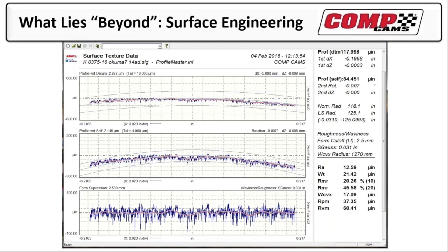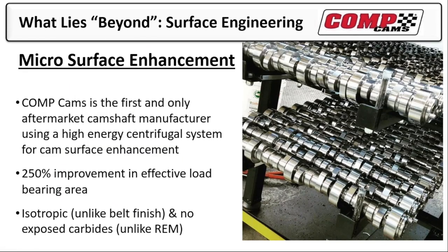About 2016, 2017, we started to go to a crown dress on all our rollers. And you can see this is very similar, but we're slightly convex. When you start looking at this, this is 300 micro inches plus and minus. Fine talcum powder is bigger than this whole scale. But you can see how we drop about 100 millionths, about a tenth of a thousandth of an inch on both sides of the load. And that made a tremendous difference.